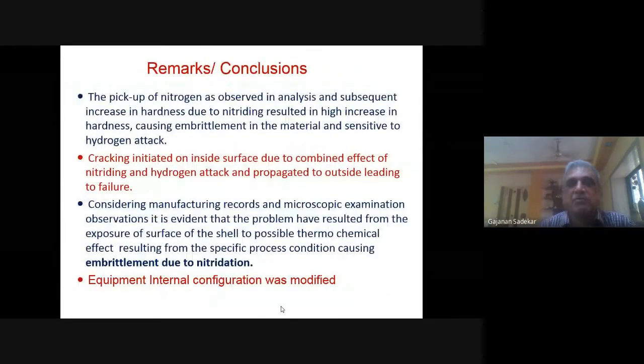And based on all these particular things, we drew the conclusion that the cracking which has occurred in this particular case is because of the presence of nitriding and the hydrogen. Okay, so pickup of the nitrogen, as observed in analysis, and the subsequent increase in hardness due to the nitriding resulted in a high increase in hardness, causing embrittlement in the material and sensitivity to hydrogen attack. Once the material became sensitive to embrittlement because of the nitriding, then hydrogen attack occurred more and hydrogen embrittlement occurred, and the cracking initiated on the inside surface.